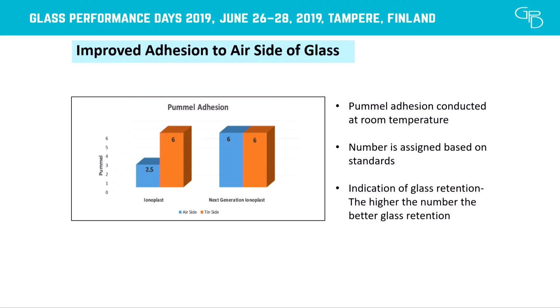Improvements to the adhesion to the air side of glass. This is a graph showing room temperature pummel adhesion, and this is next generation Ionoplast. The orange is the tin side. You can see we have good adhesion to the tin side, as expected. But if you look at the pummel adhesion to the air side, you see that it is greatly improved, so that there's basically no difference between air side and tin side adhesion. Now that's with no adhesion promoter. If you use adhesion promoter with the current SentryGlas, you have good adhesion also. So this is showing it without adhesion promoter.